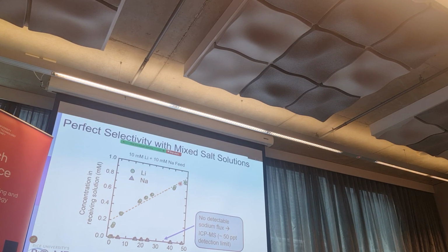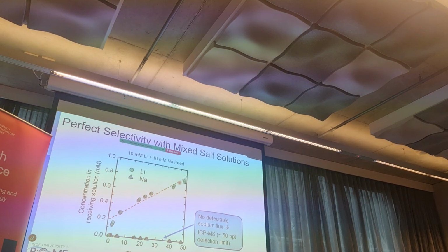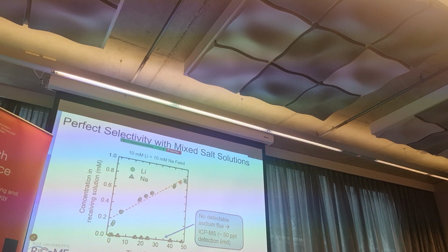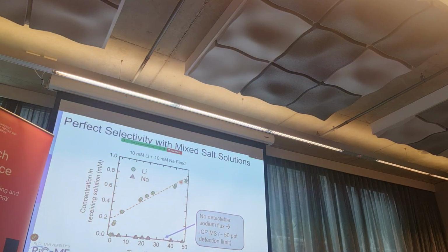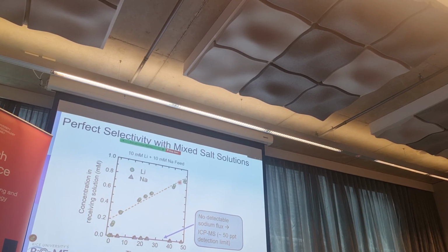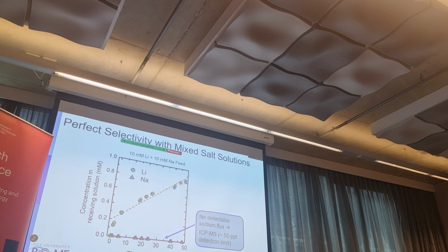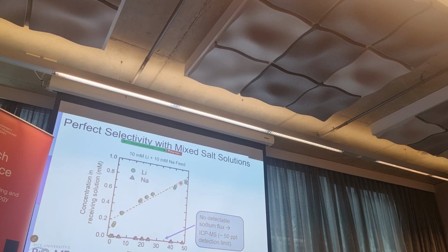So we see no detectable ion flux for sodium - you could call it infinite selectivity, but in the paper we divided it by the detection limit of ICP-MS and got a selectivity of 7,000. Nothing was detectable for the experiment; it took a very, very long time.